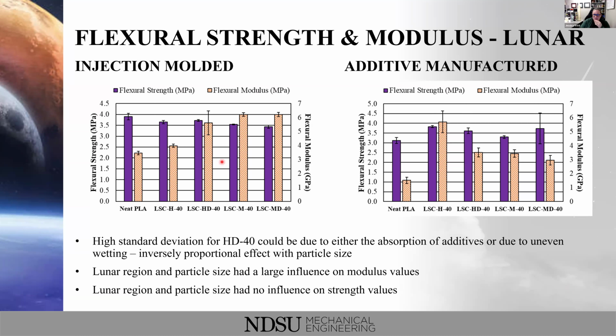And so Abby looked into this a little bit, and we believe that the polymer itself is absorbing some of the additives, or there's some uneven wetting between the polymers and the regolith simulant. And it's kind of this inverse effect. As the particle size goes down, this effect goes up, which would explain why our Highlands materials do very well. But then when we sieve them down into the dust part of that simulant, we're getting this very, very high standard deviation.